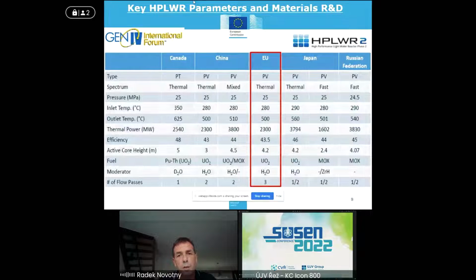If you look at the European HPLWR supercritical water-cooled reactor, we can see its parameters in this table. It's a pressure vessel type, thermal neutron spectrum, with 25 megapascal water pressure. Water is entering the core at 280 degrees C as subcritical and leaving the core at 500 degrees C as supercritical. It's a 2,300 megawatt thermal power reactor with foreseen efficiency of 43.5%, using uranium fuel, and water is working both as moderator and coolant. Water is passing 3 times before it leaves the core at 500 degrees C as supercritical water.